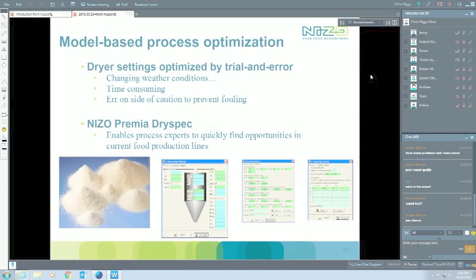And that's one thing we've been doing in model-based process optimization. Rather than optimizing with trial and error, how can we actually predict what's going to happen? That can be for when we start putting different formulations on or change conditions. The other thing you often have is changing weather conditions. Big changes in air humidity can have very large effects there as well that we need to take into account. So how can we quickly adapt to different settings if we know that our air humidity is increasing a lot and we want to prevent fouling, or if we know that we're going to have very low